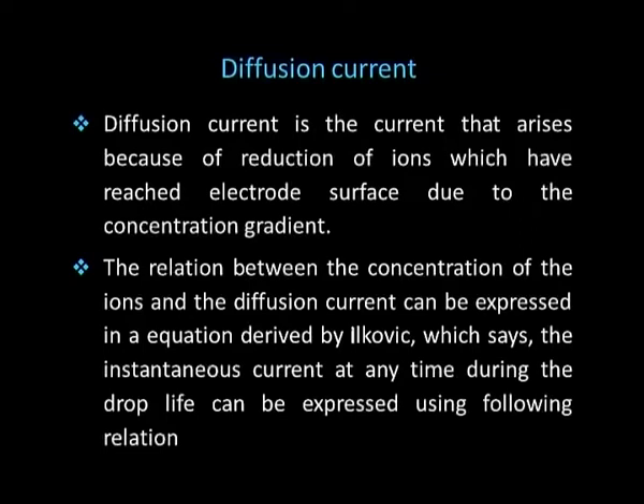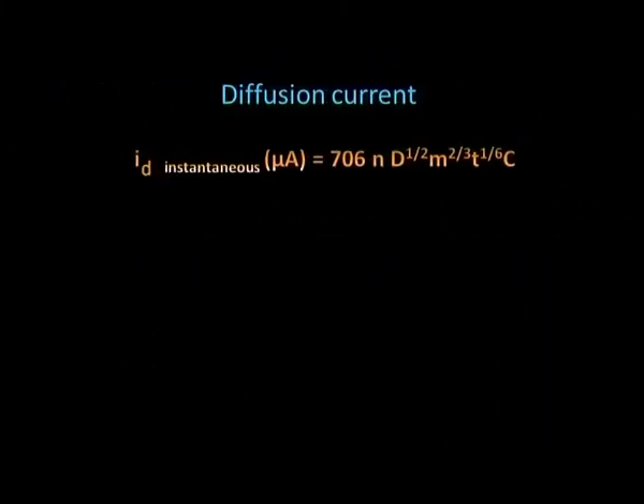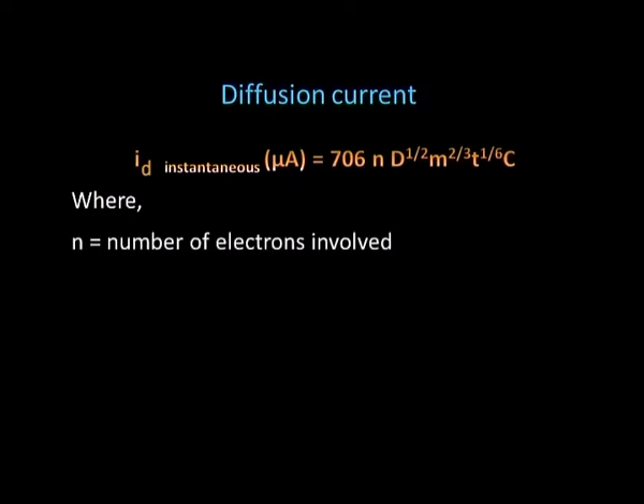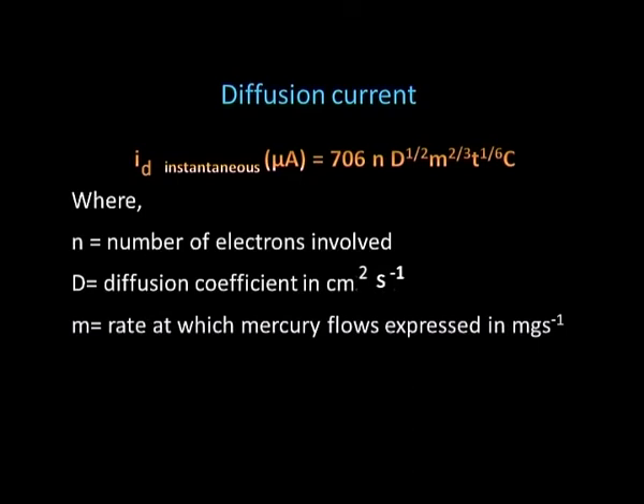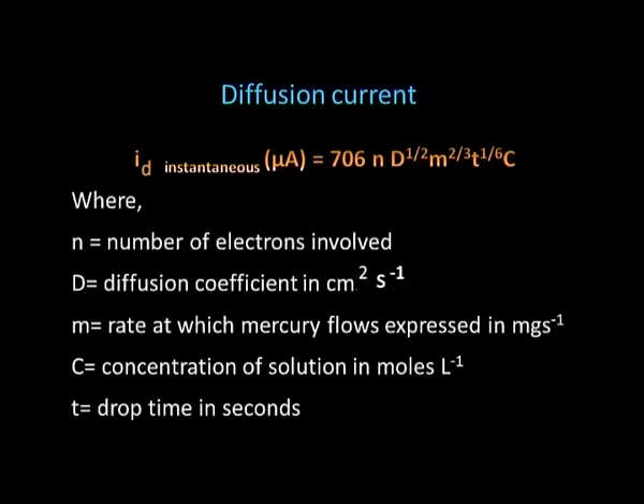derived by the scientist Ilkovic, which says the instantaneous current at any time during the drop life can be expressed using the relation Id = 706 n D^(1/2) m^(2/3) t^(1/6) C, where n is the number of electrons involved in reduction, D is the diffusion coefficient in centimeter square per second, m is the rate at which mercury flows, expressed in milligram per second, C is the concentration of solution in moles per liter, and t is the drop time in seconds.